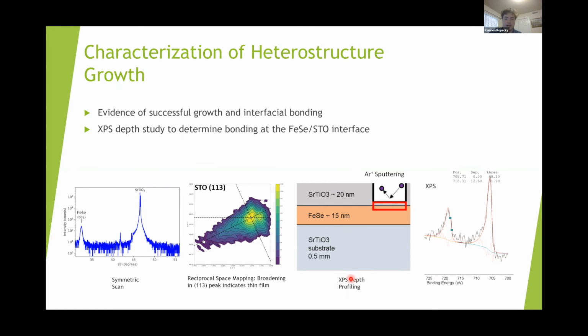And then from there, XPS depth profiling shows a sharp interface between the strontium titanate and iron selenide layers, where we can see this also through the XPS of the iron peaks, in which these iron peaks are consistent with literature values for no oxidation in the iron.